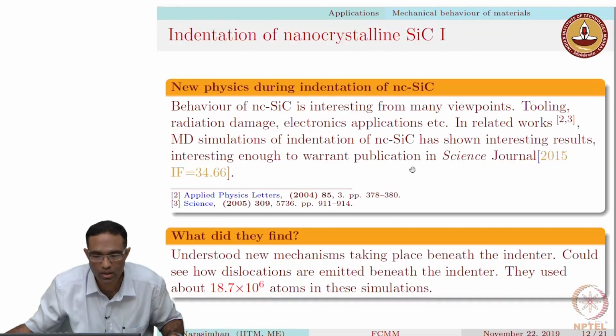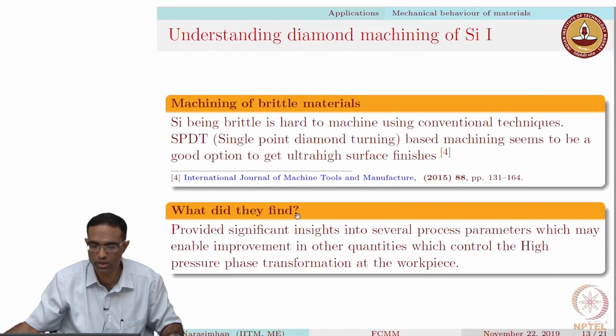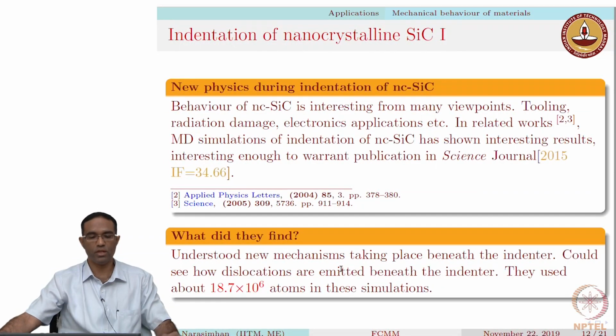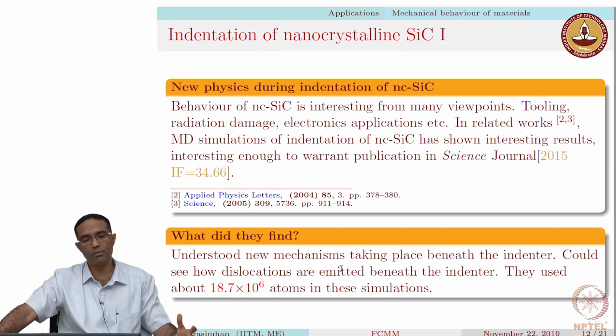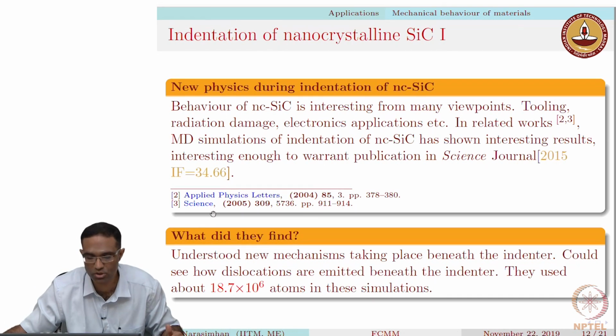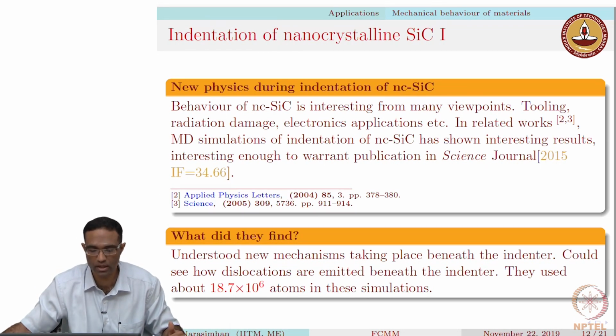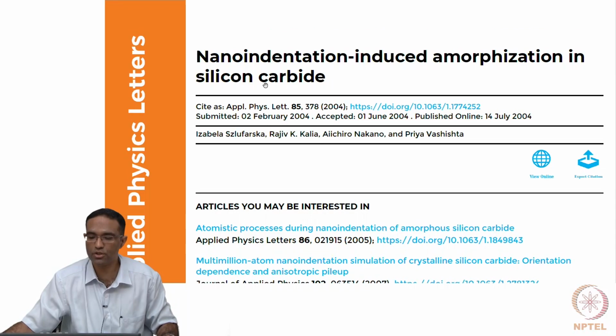Okay, so in this article, primarily they found that there are new mechanisms taking place beneath the indenter, and they could see how dislocations are emitted beneath the indenter. Of course, this dislocation emission is more clear in the Applied Physics Letters paper. This is the nanoindentation induced amorphization in silicon carbide.